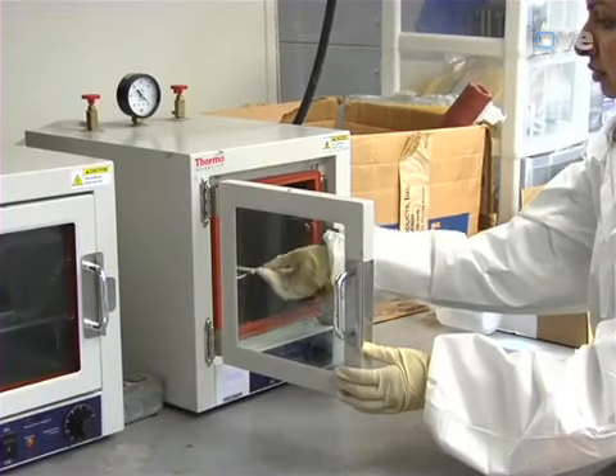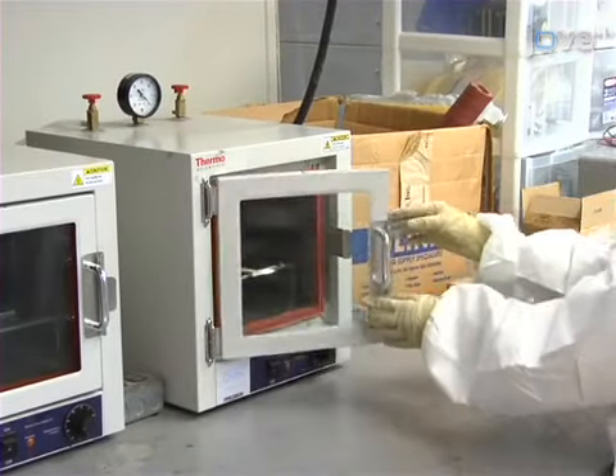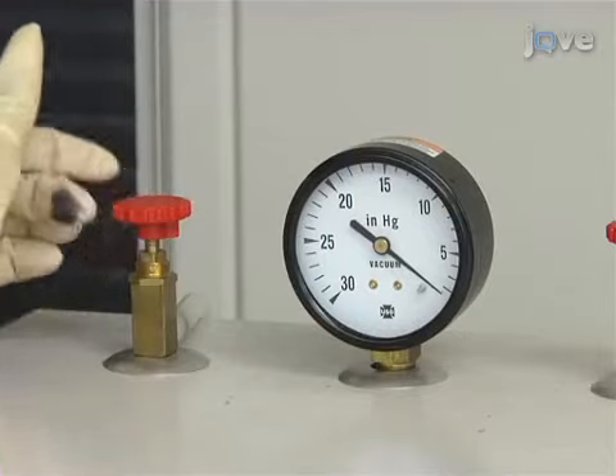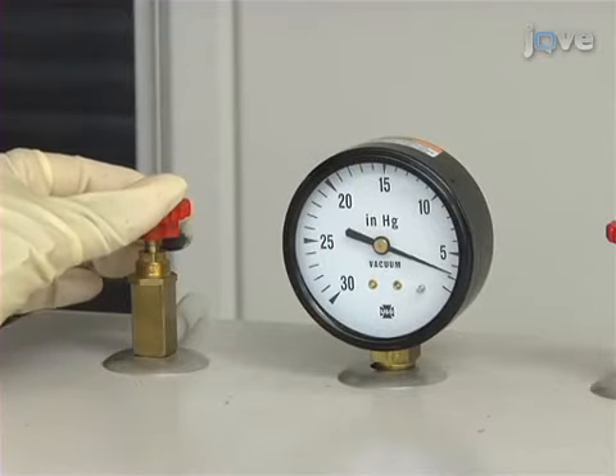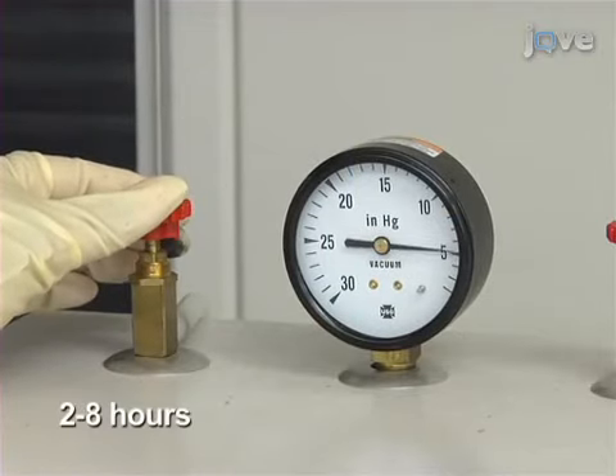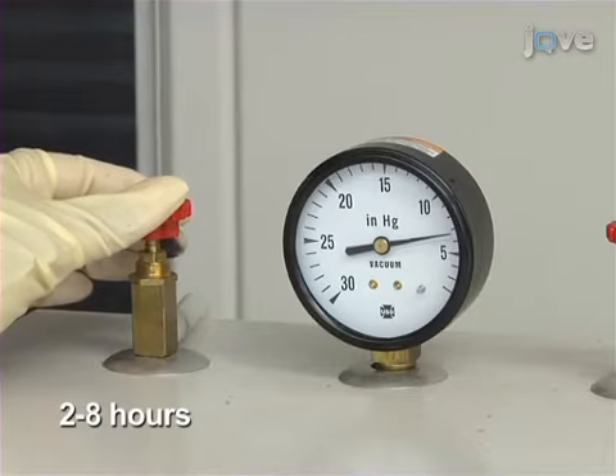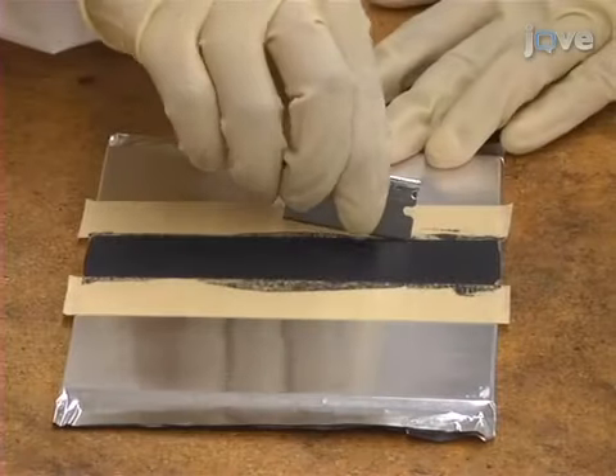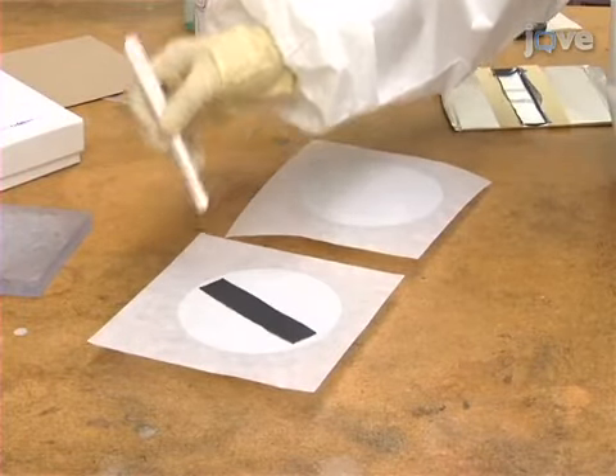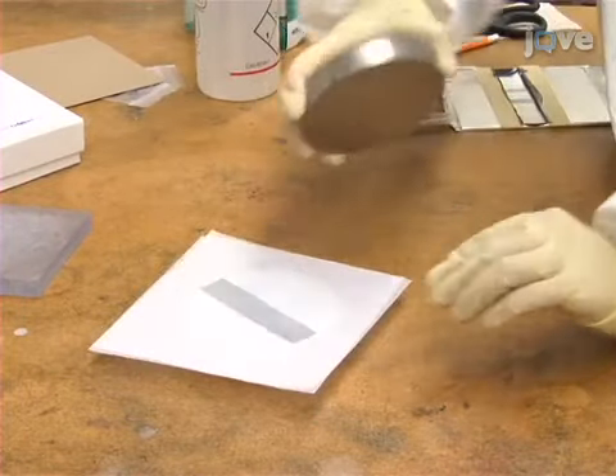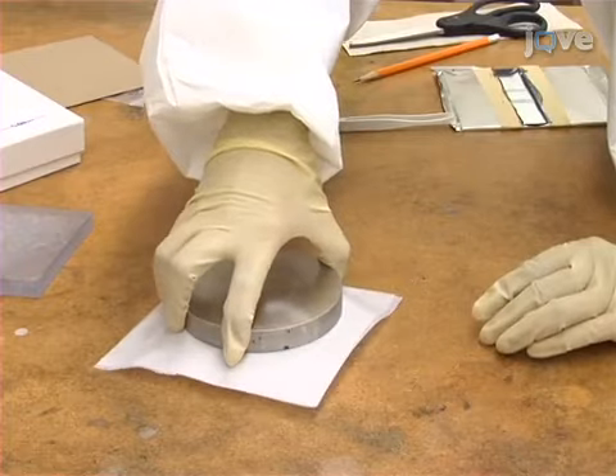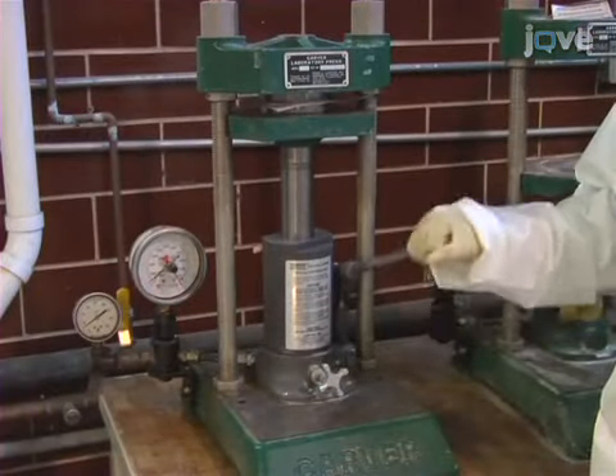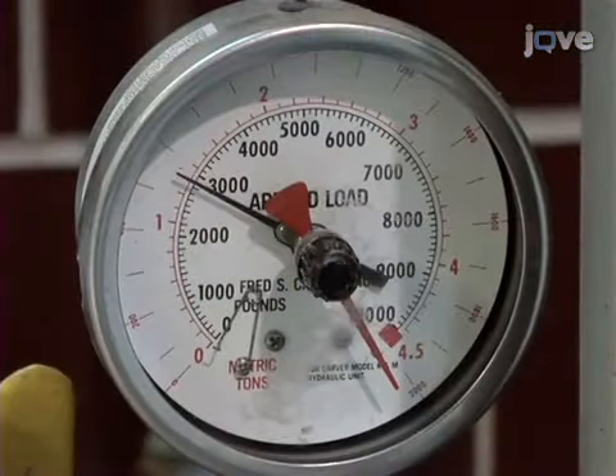Depending on the material and binder used, dry the coating in air or vacuum at approximately 90 to 120 degrees Celsius for about 2 to 8 hours. After cutting the dried coating, place the coated metal foil between 2 steel plates lined with 2 weighing papers to protect the coating. Then, press under a load of approximately 3,000 pounds.